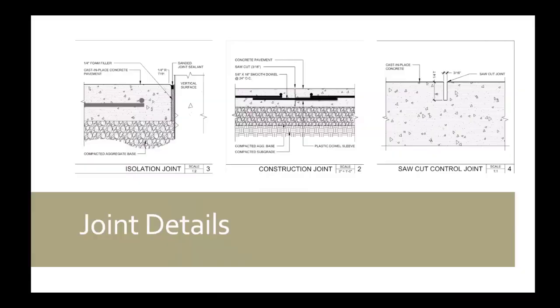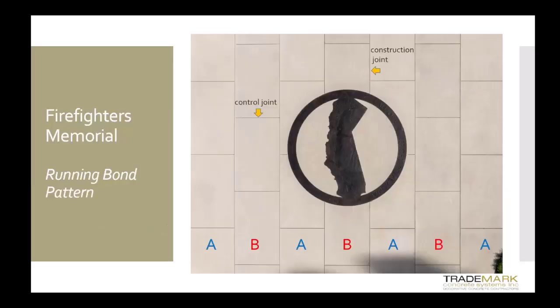So we had a 3/16 saw cut control joint, just isolation joints at the vertical structures. There were benches, sign walls that had template sandblasting. You'll see in some photos that are upcoming. Here was how we poured it. So you can see the control joint versus the construction joint. Centered in there is a bronze inlay that is 8 foot in diameter. So we kind of softened the coastline a little bit there to prevent cracking. Poured it in 3-foot wide lanes in the running bond pattern and used a color hardener for the final color.